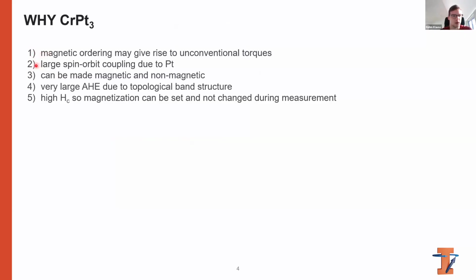The second reason is that there's a large spin-orbit coupling due to the platinum in the chromium-platinum-3. Thirdly, it can be made magnetic or non-magnetic. As I said, it's ferromagnetic in the magnetic phase, and there's a different phase where it's non-magnetic, so we can directly compare the role of magnetism in the torque generation.